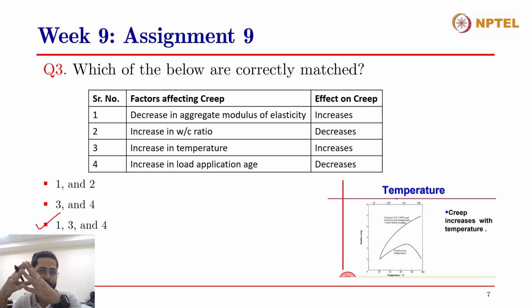It is only the cement paste part, and more importantly, it has been seen from the research that the CSH gel present in the cement paste, the cement hydration product, is responsible for creep in concrete. So it is only the cement paste part that undergoes creep in concrete and not the aggregates. Therefore, when you increase the modulus of elasticity of aggregates, the load that they can share from the concrete will also increase. So the load being shared by the aggregates gets increased, and therefore lesser load is being taken up by the cement paste. And we have seen that when the stress is less, the creep is also less. So you want aggregates with higher modulus of elasticity so that your creep will also decrease in concrete.